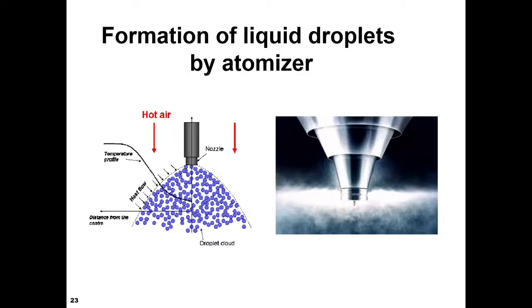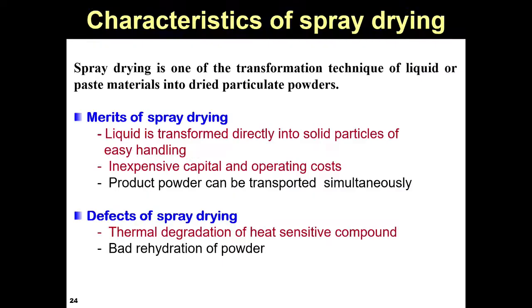Therefore, when we make the liquid droplet, the initial feed solution viscosity is important. In a high viscosity solution case, we cannot get small liquid droplets. So we have to check the feed solution viscosity, like water or some kind of soup. Viscosity is important.